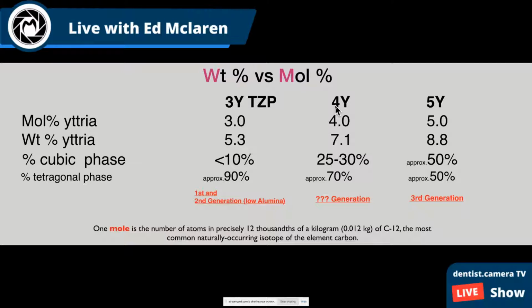If we put a little less yttria in there, what happens? So 4% of the molecules, well, we decrease the amount of cubic phase. We're still around 25, 30%, but we actually don't lose much translucency. And here's the good news. Those materials test out around 1,000, 1,100 megapascals. So I don't know what generation it is. It's a 4th generation, 6th, 9th, whatever, okay? But that's essentially what's happening.